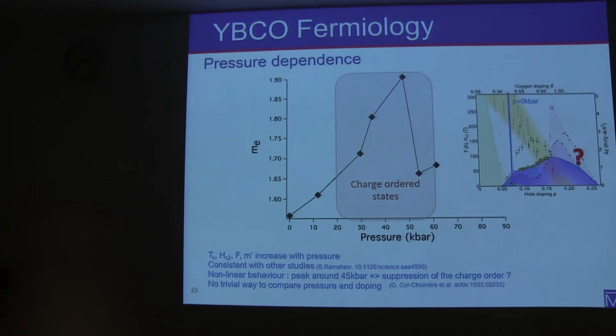Why is it that the effective mass increases beyond 1? What is the meaning of that? Normally it should be less than 1. Not really, it's a heavy Fermi liquid. Okay, so it's more on the heavy Fermi side, or like strongly correlated systems. Yes, that's what you expect. This is what is observed already for the samples tuned with doping. So there is nothing surprising for us here. For the sample that's here, the effective mass is also of the order of 1.9. So we are in really good agreement with what's been done with doping.